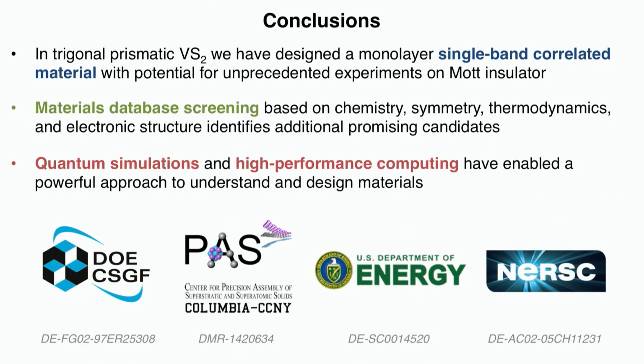So with that, I'd like to conclude that in trigonal prismatic vanadium disulfide, we've engineered this single-band correlated material. And if synthesized, this could enable really unprecedented experiments on a strongly correlated material. We then took a more systematic approach based on a materials database screening with a query based on several factors and generated several additional candidates. And finally, I hope I've given you a flavor for how high-performance computing, quantum simulations, and in addition, this new area of materials informatics can enable us to design or discover materials, even with very particular, very specific electronic properties.